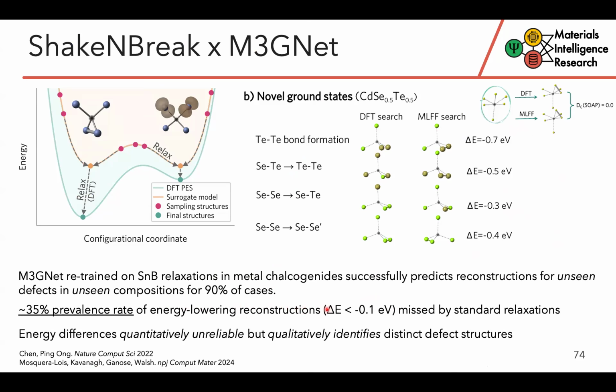I will say that this is still, of course, within our chemically constrained subset of neutral cation vacancies in metal chalcogenides, but still, to us, it was quite a promising result, showing that when trained properly and appropriately, and on the right sort of data, these machine learned interatomic potentials could reproduce the behavior we were seeing from high-level DFT calculations. And so we took it as a promising sign for the potential utility of some of these machine learned interatomic potential approaches for defect solids.